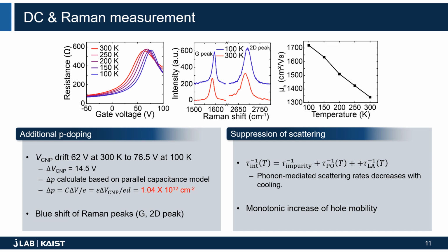First, to investigate the temperature dependence of carrier concentration and the mobility of graphene, we measure the DC electric properties of graphene while varying its temperature from 300 to 100 Kelvin using a nitrogen purge cooling stage. The charge neutrality point drifts from 62 volts at 300 Kelvin to 76.5 volts at 100 Kelvin. The shift of the CNP is 14.5 volts, corresponding to an additional hole doping of 1.04 times 10 to the 12.